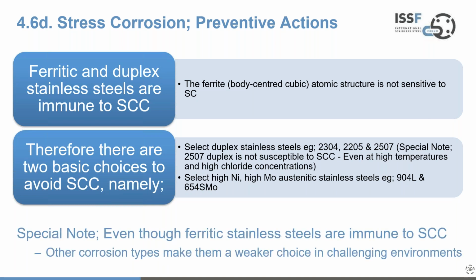But there is again a note of caution here. Even though ferritic stainless steels are pretty much immune to stress corrosion cracking, because they are weaker as a choice in other corrosion mechanisms, where those other mechanisms are present, they are not necessarily the most favoured choice. So you have to think about what other corrosion mechanisms are likely to be present.